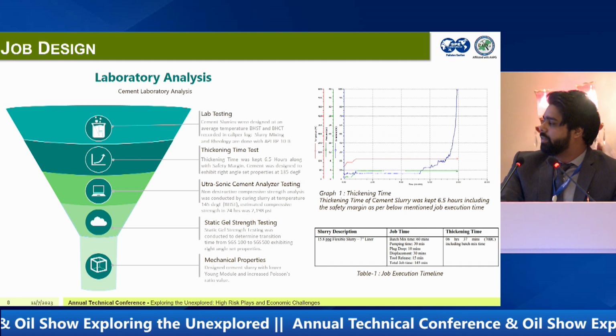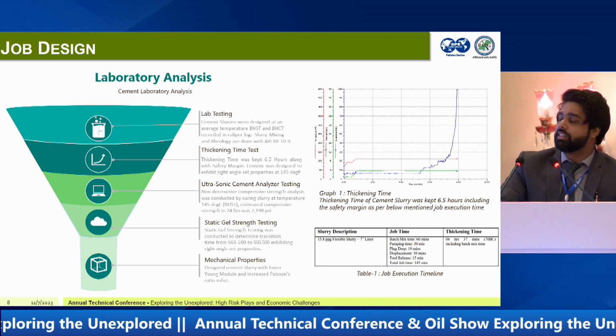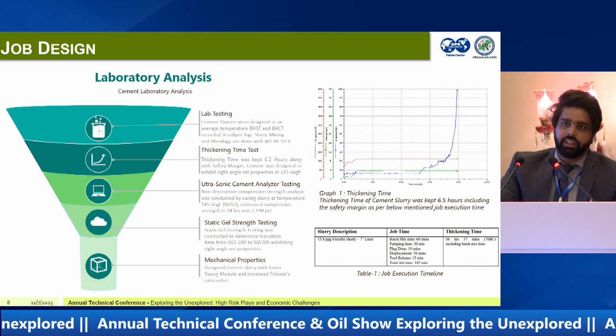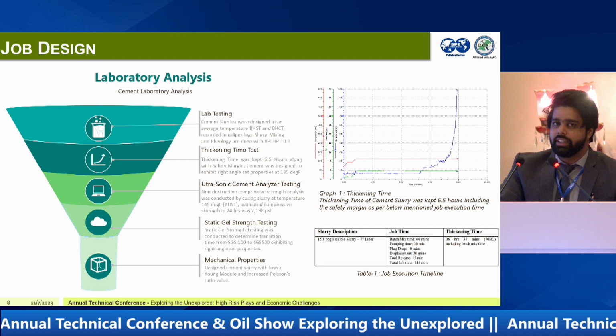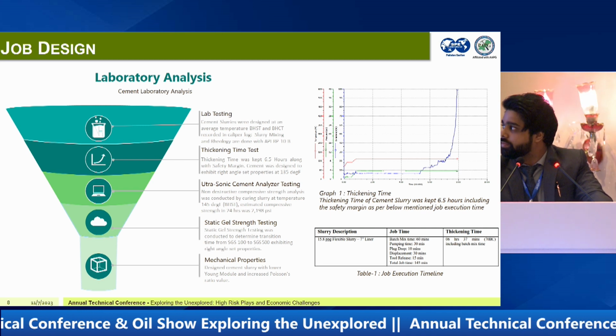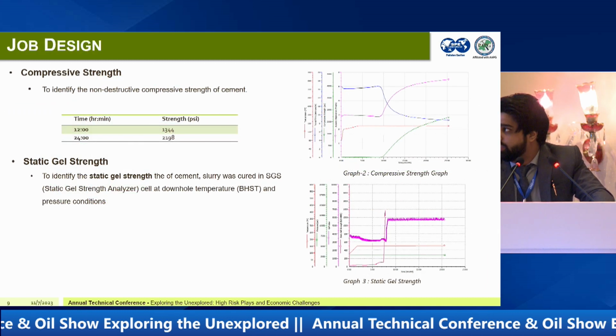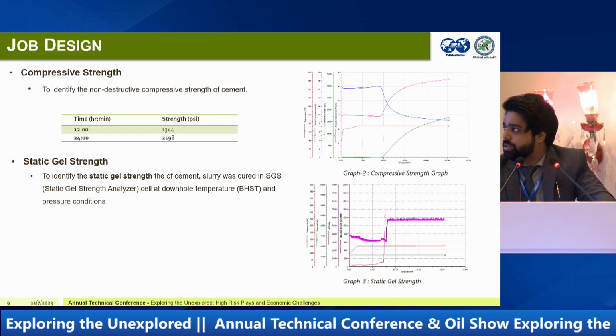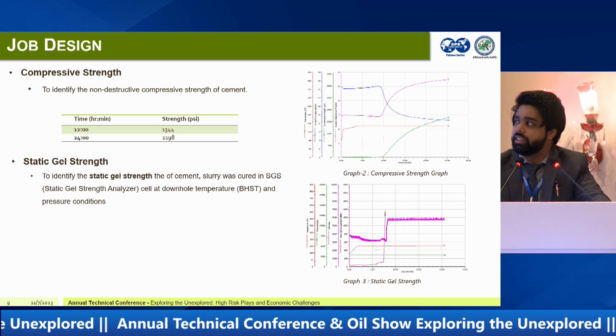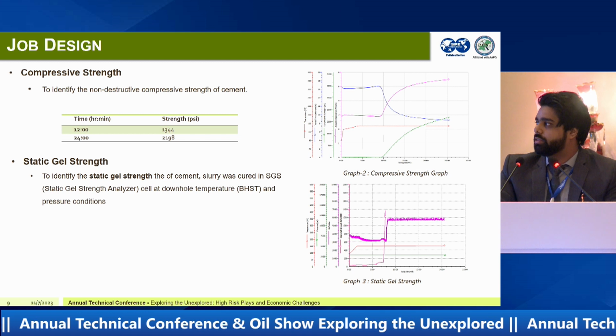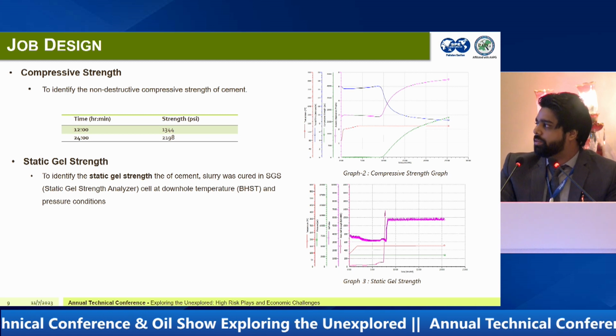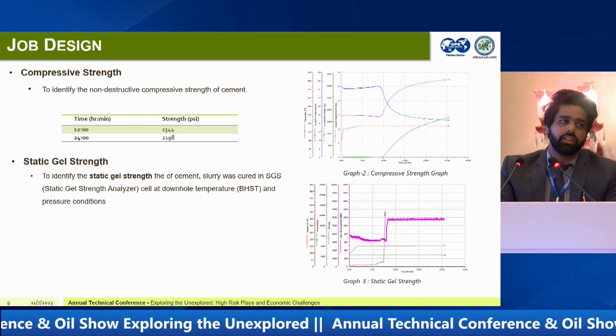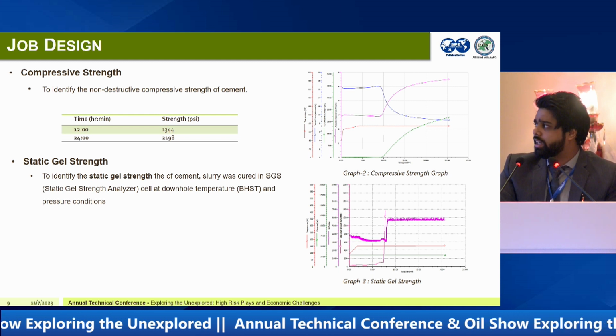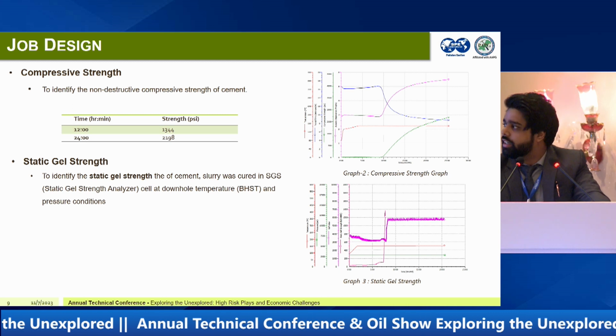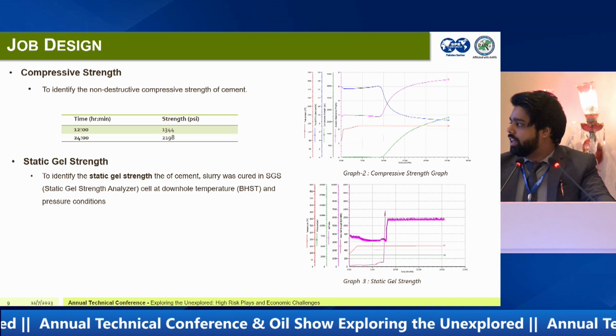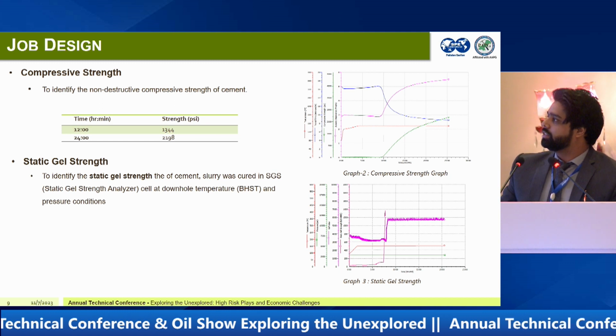You can see from the graph that we proposed almost 6.5 hours of thickening time for the job, whereas the total time required was 145 minutes. We included a safety factor while designing the job. Similarly, the table shows that we had rapid compressive strength around the top of liner. In 12 hours, we usually get approximately 1400 psi, and for 24 hours, we had 2200 psi. Similarly, we also conducted a static gel strength test at bottom hole static temperature. The graph depicts the design parameters.